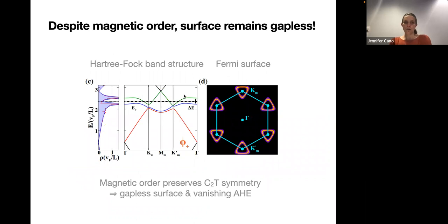Now, I mentioned earlier that for ferromagnetic order, the surface of the TI would be gapped, and you can measure quantized anomalous Hall effect. But here, the surface remains gapless because there's a lot of symmetry preserved even with this magnetic order. And so we see that there's not a full gap that opens on the surface, but the density of states does split. That's what makes this reduce the total energy of the system. And so this rather weird order results in a gapless magnetic surface state.